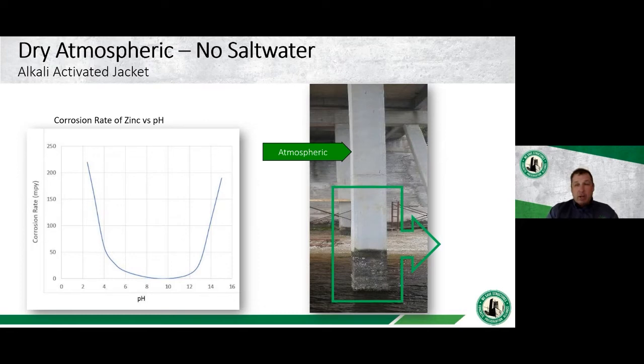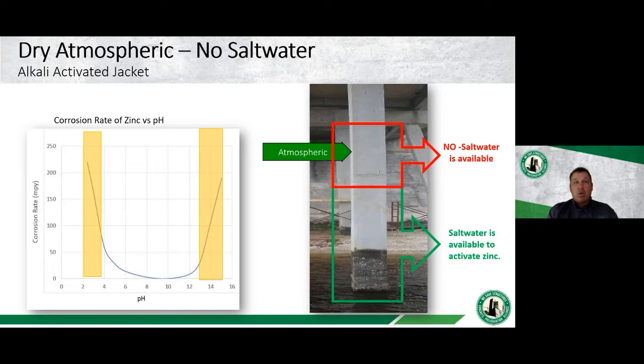We know down here in the lower portions, we can rely on the salt water to activate zinc. But as we move into the higher portions, we do not have any salt water that's available. And if you actually look at the corrosion rate of zinc versus pH, zinc corrodes either in a low pH environment or in a high pH environment. So we're going to look at trying to use one of these environments to keep the zinc in an active state, because we have no salt water available. Without that salt water, we can't keep it activated. So let's try and figure out something else. What else can we use to activate it?